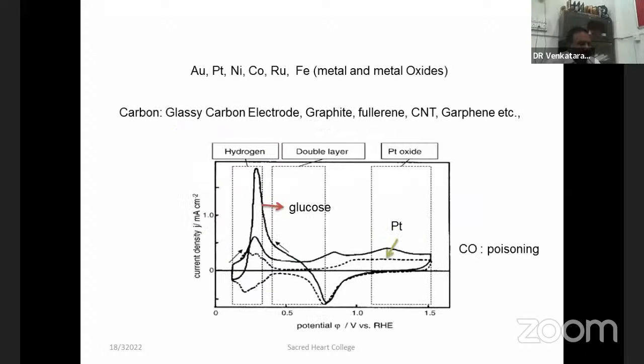And here, for example, if you look at the application of platinum, the solid line is the reaction of glucose on platinum, but this peak is not highly reproducible. One important parameter of a sensor for medical application is that it should be accurate. Whenever you use a sensor, it should show the same value. Only then can it be applied for diagnostics, to accurately diagnose the disease. But here, once it completes the cycle, if you come back to the second cycle, it almost becomes zero, because platinum oxidizes glucose into carbon monoxide and water. This carbon monoxide will strongly adsorb on the metal surface. So direct sensing of glucose at the metal surface is quite difficult.